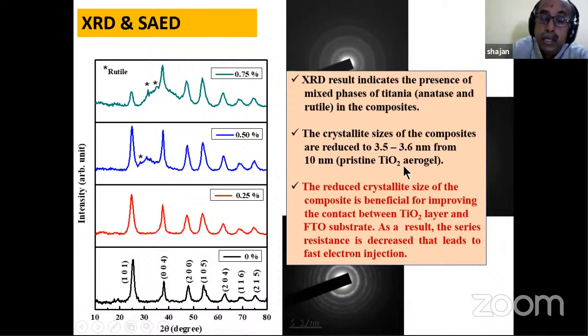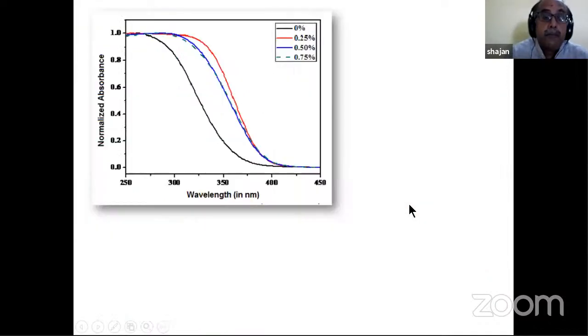And the reduced crystallite size is beneficial for improving the contact between the FTO and the TiO2 substrate. And that is supported, because later results show that the interfacial resistance, the series resistance, is coming down, and therefore there's a fast electron injection.